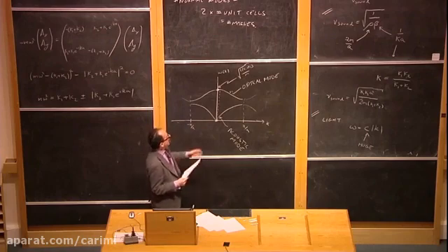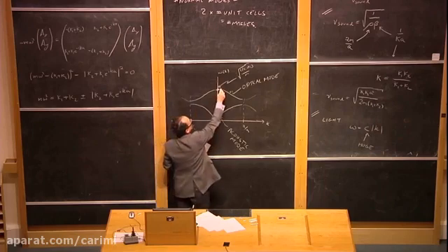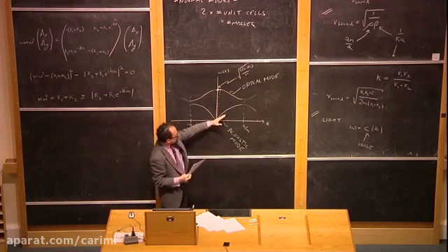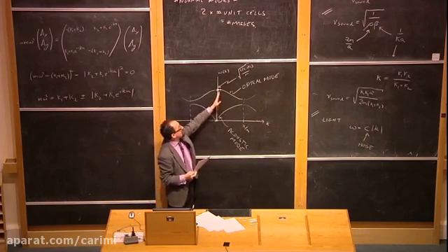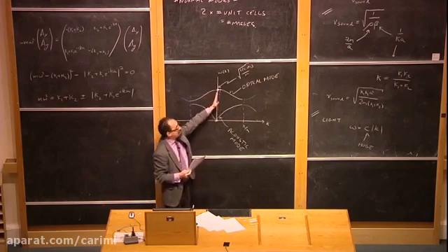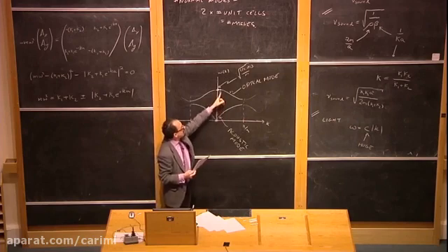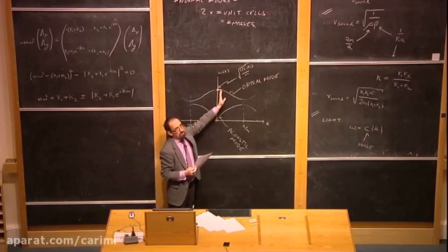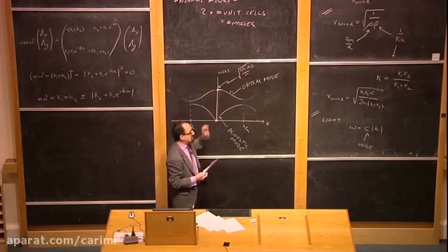So you have to match up both the frequency and the wave vector of the light with the frequency and the wave vector of a phonon. The only place that can happen is right here. And the reason you're never going to match the acoustic mode is because the velocity mismatches so badly. But with the optical mode, since the optical mode has finite frequency even at k equals 0, there is a point where the optical mode frequency matches the light frequency and the optical mode momentum matches the light momentum, or even crystal momentum in this case.